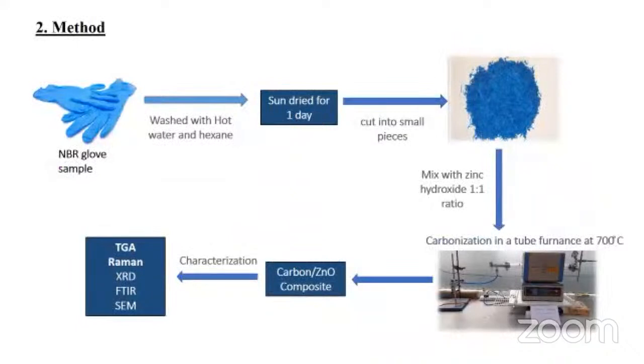This is the proposed method of our work to convert these nitrile gloves into a value-added product. First, we collected the nitrile glove samples from the laboratories and washed them with hot water and hexane to remove all the adhered impurities. Then the samples were sun-dried for 1 day. After that, the samples were cut into small pieces and mixed with the zinc hydroxide in a 1:1 ratio and carbonized in a tube furnace at 700 degrees in an inert atmosphere. After the carbonization, the obtained sample was ground into powder form to synthesize the sensing materials. The material was further characterized using TGA, Raman, XRD, FTIR and SEM techniques.